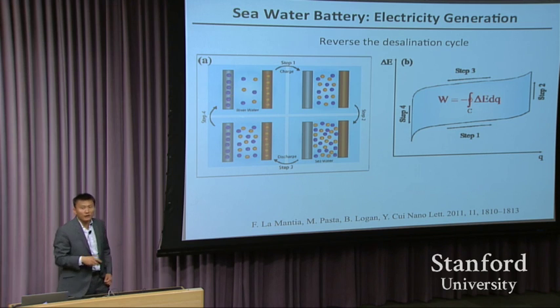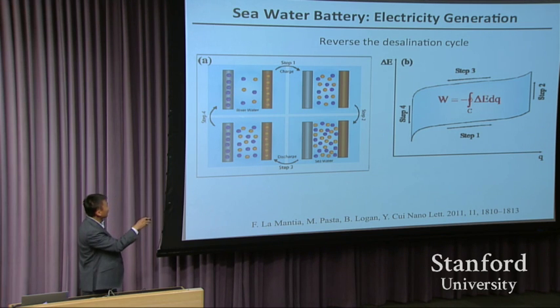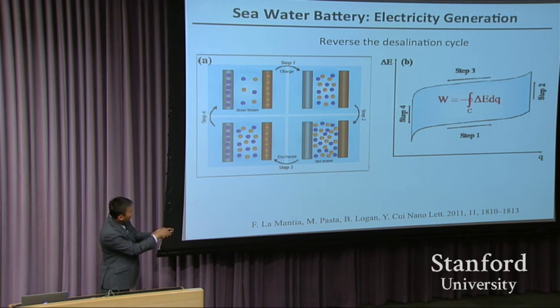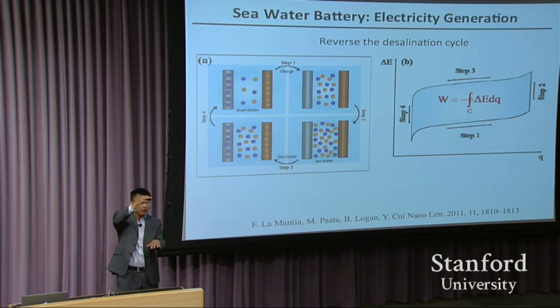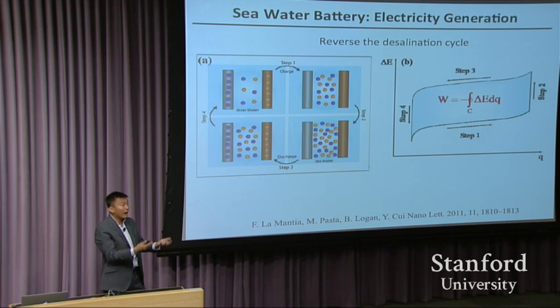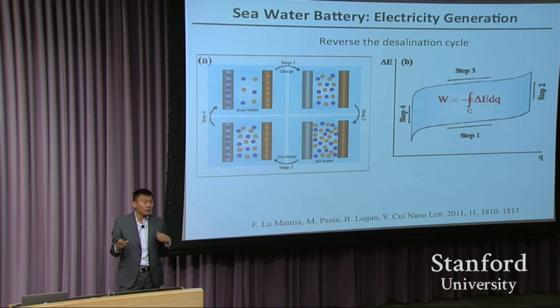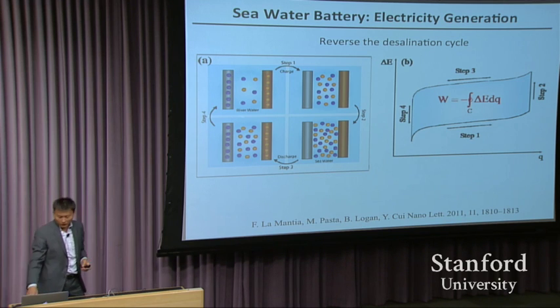Now what you do is you charge up your battery in the river water. You put the ions into the river water. And then you flow in the seawater. You take out this. You flow in the seawater. And then you do the discharge, step 3. So now this becomes charging, this becomes discharge. It turns out the discharge voltage is higher than the charging voltage. You gain energy out of it. So you actually take out the energy from the salt concentration difference between river water and the seawater.